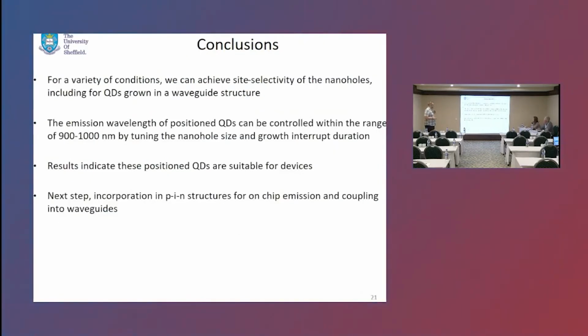In conclusion, for a variety of conditions, we can control the position of the quantum dots. We can tune the wavelength. We've recently done experiments where we chop the tops off the dots to bring them back, but we haven't sort of got that all sorted out yet to present. But we're in the right range for silicon detectors, for free space quantum optics, from mountaintop to mountaintop, or short distance fiber. We have dots, and we can do this by tuning the nanohole size and the growth interrupt.